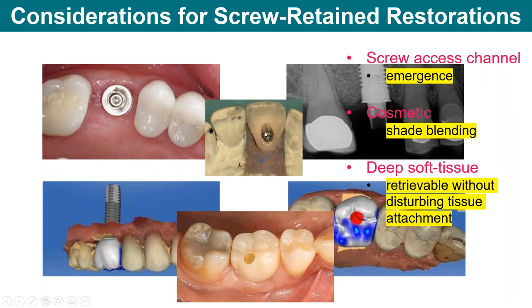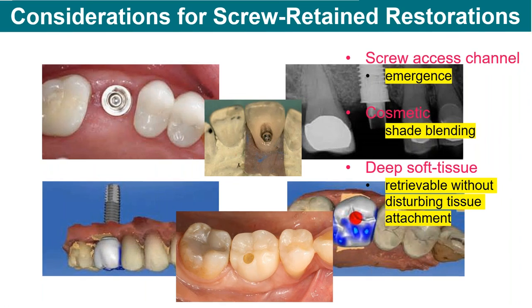And sometimes cosmetically, if the implant is placed well, then you can do pretty much either cement retain or screw retain. It's just that when you get to a point where this is iffy, right? If you're under a stamping cusp and you have your screw access hole right there, that access is going to create more forces distributed down. And you can also see that there's a wear on your composite that you've patched up. So you need to make sure and treatment plan correctly, cement retained or screw retained accordingly.